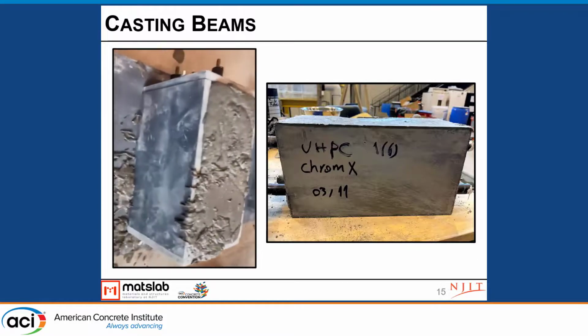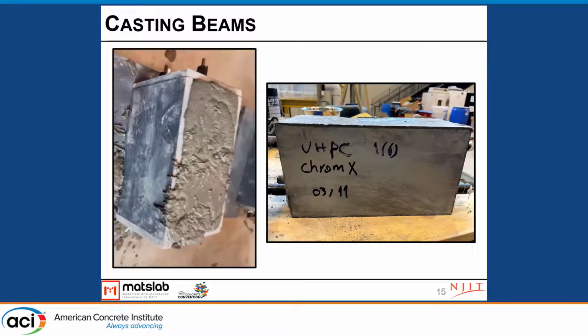But if you do the same for UHPC, probably you cannot finish it, because these materials get hard relatively fast at the surface. Not completely hard, but hard enough that you cannot get a nice finish. So it's better to do it as soon as possible. But after demolding, we got a very nice specimen. You barely can find any defects or air bubbles at any side of the specimens, and we also got a nice finish at the top too.